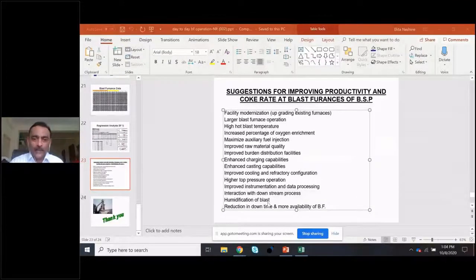But the beautiful part is that hydrogen is a very thin gas compared to carbon monoxide. So the gas-solid reaction with hydrogen is better than with carbon monoxide, but it will happen nicely at somewhat higher temperature. The furnaces which are operating at high temperature will inject more steam and get the benefit. So, reduction in downtime and more availability of the blast furnace.